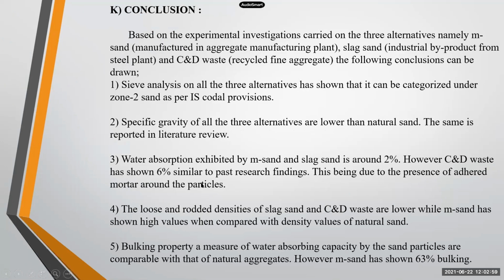Conclusion. Based on the experimental investigation carried out on the three alternatives, namely M sand, manufactured aggregate from a manufacturing plant, slag sand, an industrial by-product from steel plants, and C&D waste, recycled fine aggregate, the following conclusions can be drawn. First, sieve analysis on all three alternatives has shown that they can be categorized under zone 2 sand as per Indian Standard codal provisions.